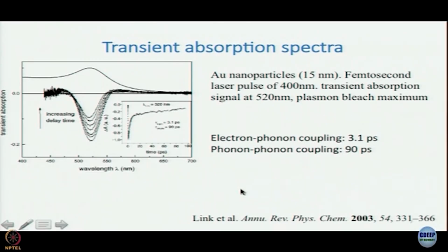And what Link and El Sayed and other people did was that they looked at the ground state bleach recovery dynamics, and they got two time constants. You can see the trace here, two time constants 3.1 picosecond and 90 picosecond. 3.1 picosecond was assigned to electron phonon coupling, and the longer 90 picosecond component was assigned to phonon-phonon coupling. So, what did they not see? What is it that they missed?